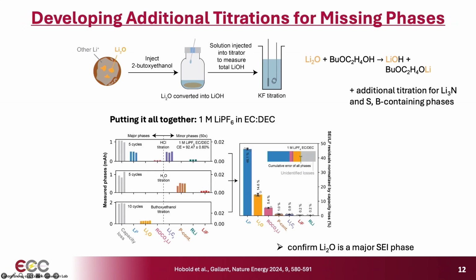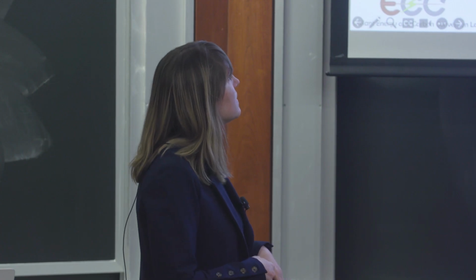So coming back to the electrolyte that I just showed you, you can see that we did, in fact, detect lithium oxide there, and it wound up being actually the most prevalent SEI phase in this particular electrolyte. So we're really starting to chip away at the unknown. So we can confirm lithium oxide is there.